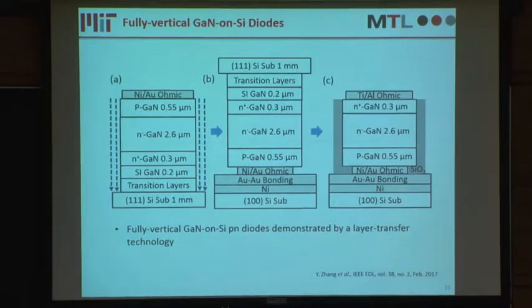So we demonstrate this fully vertical device by using a layer transfer technology. We first etched down to the silicon substrate in the original GaN silicon wafer. Then we flip over the whole wafer and bond it to another silicon substrate, and we removed the silicon substrate and the transition layers in the original GaN silicon wafer.